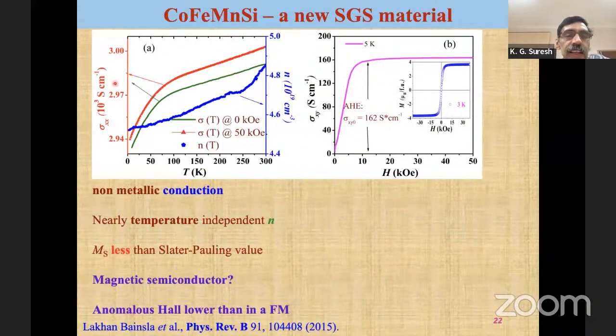So this is the conductivity of this particular material. This is one of the first materials that we identified, CoFeMnSi. So you can see that the conductivity is not that of a metallic system because it's increasing. It's not resistivity, it's conductivity. Then, of course, there are various measurements we can do. This is the Hall. Sigma XY is the Hall.